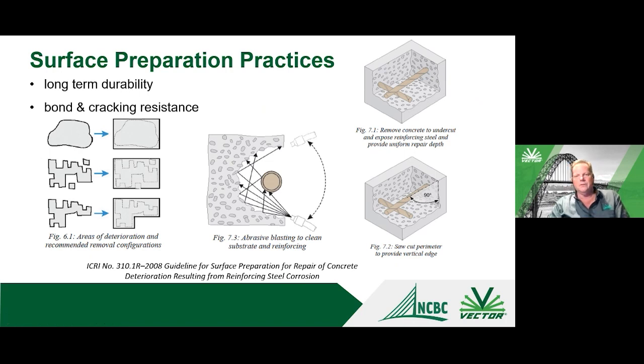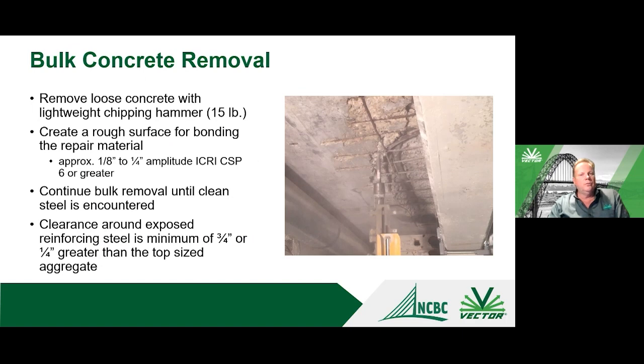And here you should see an illustration of a blast cleaning where the aggregates or the blast media is reflecting off the back of the repair and reflecting onto the back of the steel. Bulk concrete removal, this is when you're going to be chipping out basically loose concrete, and also, as I mentioned, you're probably going to be chipping into sound concrete just to make sure that you get the right geometry of your repairs. We want to make sure that we don't do too much damage to the concrete, so the weight